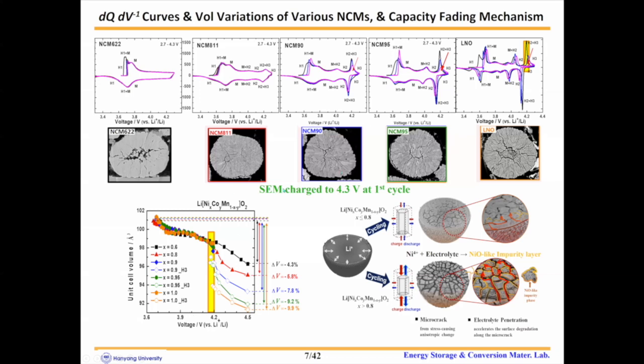And these are the cross-sectional SEM images charged to 4.3 volt after cycles. As you can see, the micro cracks observed in the cycled 622 and 811 NCMs were arrested before reaching the particle outer surface. However, the NCM 96 and the LNO exhibit an increased amount of micro cracks which propagated to the particle outer surface.